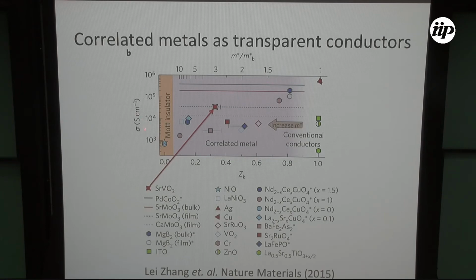And everything is summarized in this diagram. Here you have the conductivity. Here you have the ratio of the renormalized effective mass to the bare effective mass, and this is the effective mass renormalization factor. If it's 1, you are here in the simple metals where there are no correlations whatsoever. If you start introducing correlations, Z starts to go to the left, increasing the effective mass. And here is strontium vanadate. There is a lot of large mass renormalization, but still we are in the metallic regime. It's a correlated metal, and only crossing this line you get to the Mott insulator.